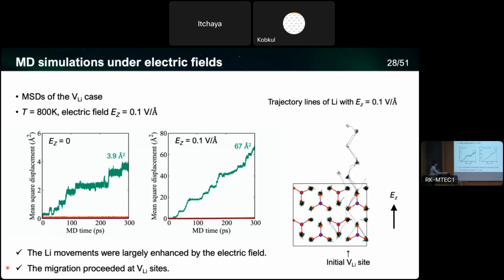The electric field is applied in the vertical direction. And as you can see, the lithium is migrating along the electric field. And we can see the trajectory only in this region because we initially have lithium vacancies at around this position. So this result is quite reasonable.